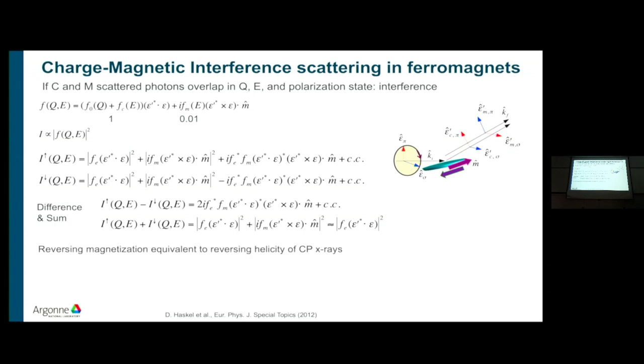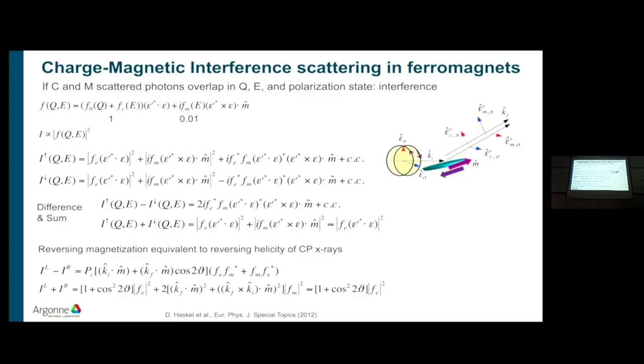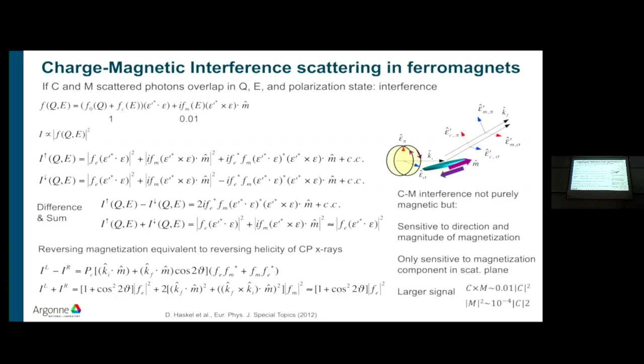And the nice part is that reversing magnetization direction is equivalent to reversing the helicity of the circularly polarized X-rays. So I can do the same experiment by flipping the helicity and keeping the magnetization fixed. And here what I've done, a little bit of algebra to convert these polarization unit vectors into Ki and Kf. It's just some geometry that is not super important at the moment, but it's very simple. You see that you're sensitive to the magnetization in the scattering plane, projections along Ki and Kf. Ki and Kf are the incident and scattered wave vectors. The M is in the sample that is scattered. That's right.